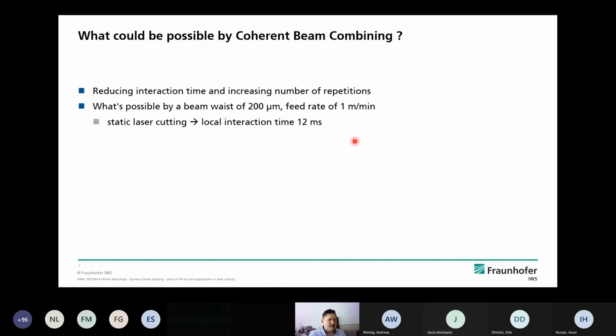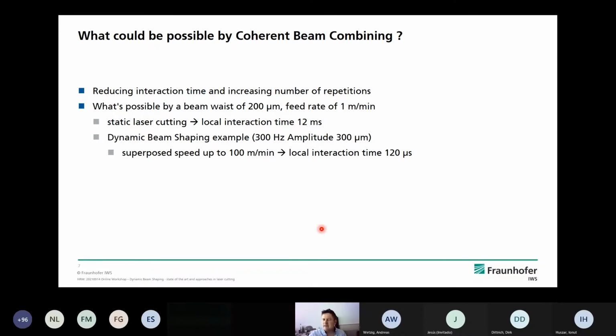That means for a static beam, we have an interaction time between material and beam of 12 milliseconds. If we consider dynamic beam shaping with a frequency of 300 hertz and 300 microns, it's a sine function. We can also calculate the superposed speed of the moved beam. So the moved beam of dynamic beam shaping will be in a range of 100 meters per minute. That means we can reduce the local interaction time from 12 milliseconds down to 120 microseconds.